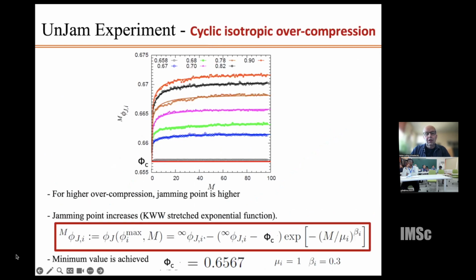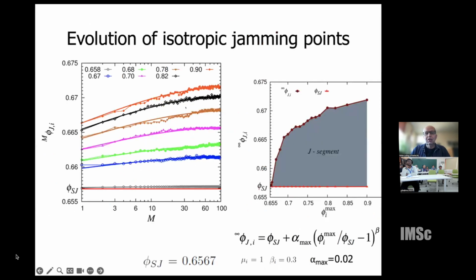You can go further. I don't want to go into details here, but this is logarithmic long-term aging. I only give you the keyword. I don't tell you the details. This is the proof or the confirmation that the jamming density or the solidification density is a function of history. For different history, you get different densities in this gray area. So the consolidation density, the jamming density, however you call it, I do not call it yield density. The jamming density is a function of history. The yield density is another story. That's not the same thing.